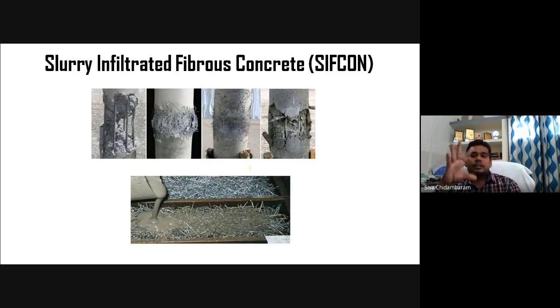100 megapascal, just like this. 100 megapascal concrete you can easily attain with this. And the flexural strength to compression strength ratio is very high. It's unimaginable. Okay, these are various advantages of this SIFCON, in which the fiber will be randomly oriented or perfectly oriented layer by layer, and then slurry will be infiltrated, and the second layer will be placed, slurry will be infiltrated, the third layer will be placed, again slurry will be infiltrated. So this is how we have to make it.